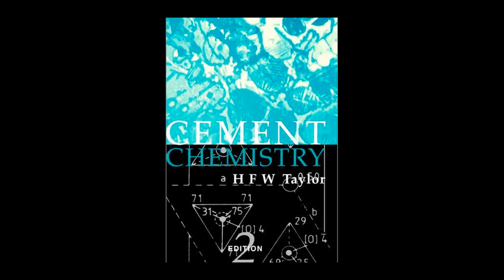So if the kiln operator allows the cooling process to stall in that critical temperature range, they're literally producing dust instead of cement clinker. That's a massive economic failure baked right into the process. It is a critical kinetic failure. And just like alite, belite is stabilized by substituting these foreign elements. Belite is often a sink for things like K2O, Na2O, TiO2, P2O5, and Mn2O3. And these substitutions are what stabilize the desired hydraulic beta form, preventing that transition to the inert gamma form during cooling. So elements that might be minor in the overall clinker composition play this disproportionately large role in making sure belite actually contributes to strength.